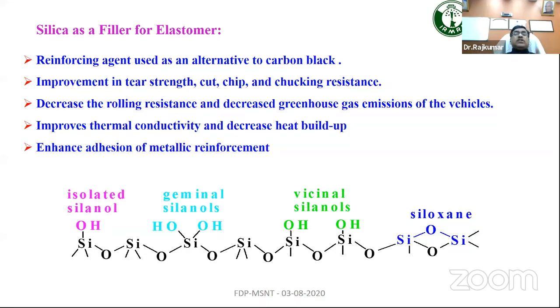Now what happens is, in order to prepare 1 ton of carbon black, an equivalent 1 ton of carbon dioxide is emitted. That means if you replace 5 parts, 10 parts of carbon black by silica or any alternate material, you save an equivalent amount of carbon dioxide emissions in the environment. So it leads to environmental savings and other things. So that is a trend now. It also improves thermal conductivity. So silica is useful for elastomers, especially natural rubber SBR blends. The tire industry is trying to use these techniques.